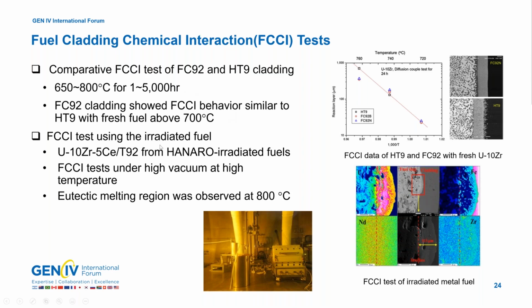And also, using the fuel irradiated in Hanaro to about 3% burnup, we did an annealing test in the hot cell to check the FCCI behavior. This shows the annealing test equipment inside the hot cell. This shows the FCCI test result of this fuel, and at about 800 some eutectic reaction was found. So through this test, we made a database to confirm our fuel behavior and to be used for our licensing purpose later.